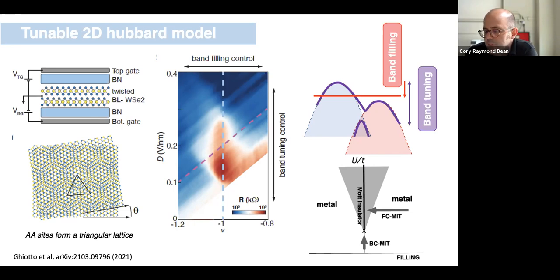Now, what's interesting about this experimentally is that generally this kind of tunability, although you might access this phase diagram in more conventional systems, is not necessarily accessible in a dynamic way in a single material. You might have to, for example, vary the doping through substitutional doping, et cetera, which might be varying other constants of the system. And you might have to vary the precise nature of the band structure through some other complicated means. But here, just through field effect gating, we can get access to both of these axes.